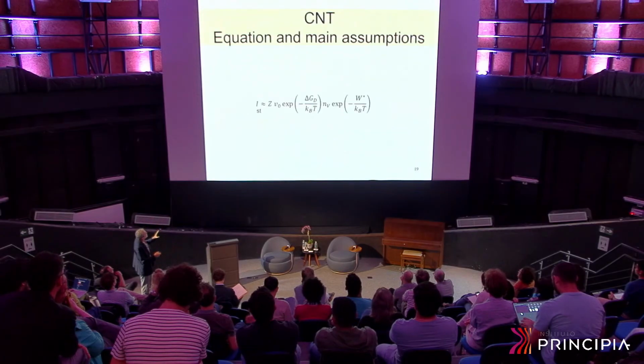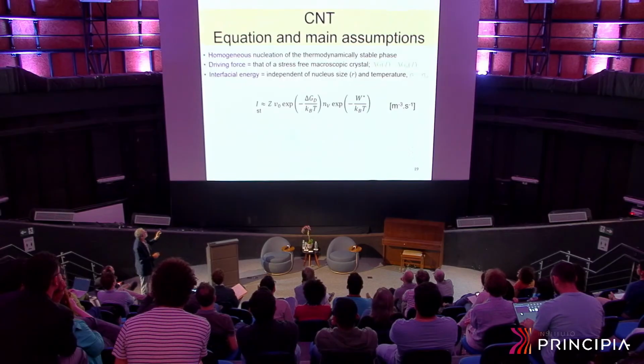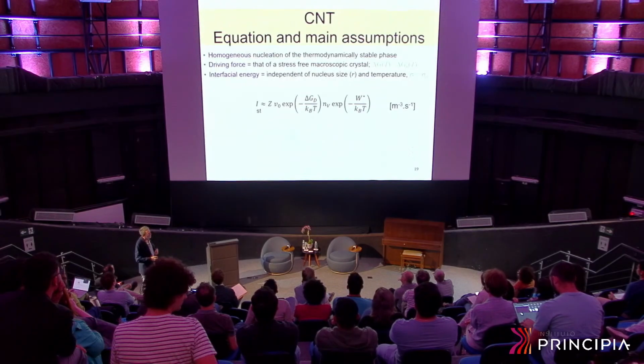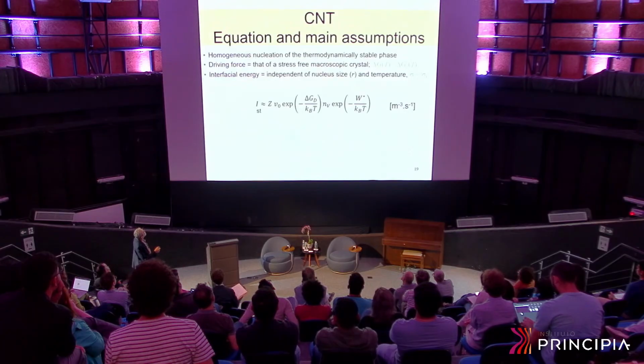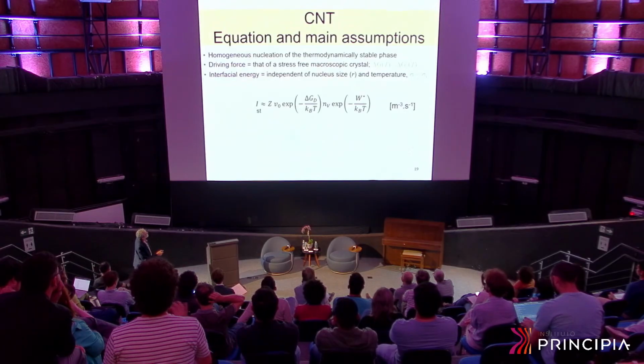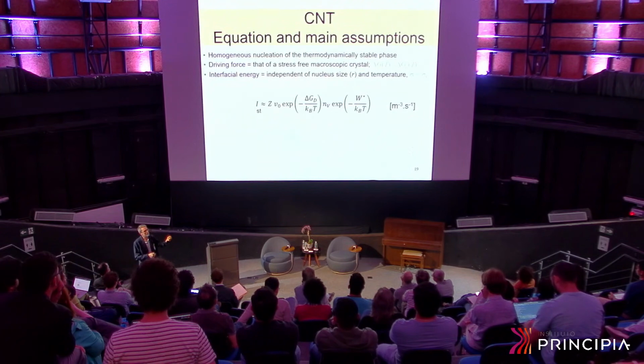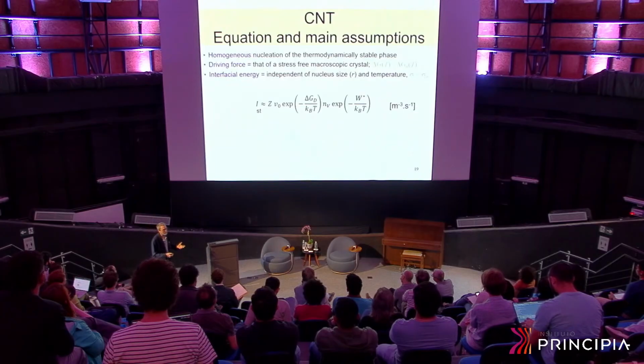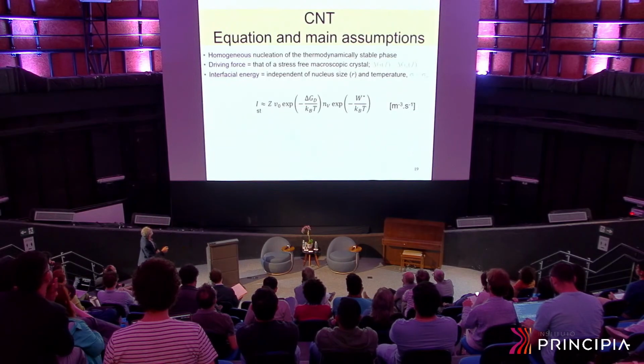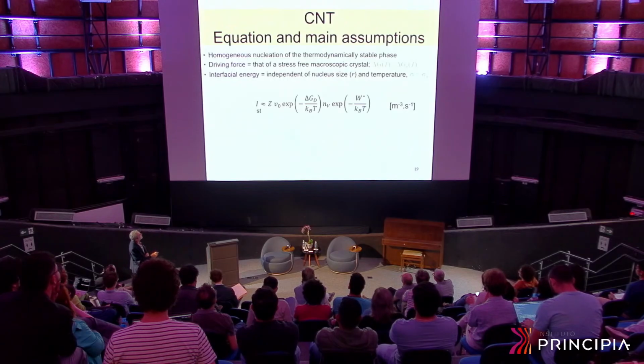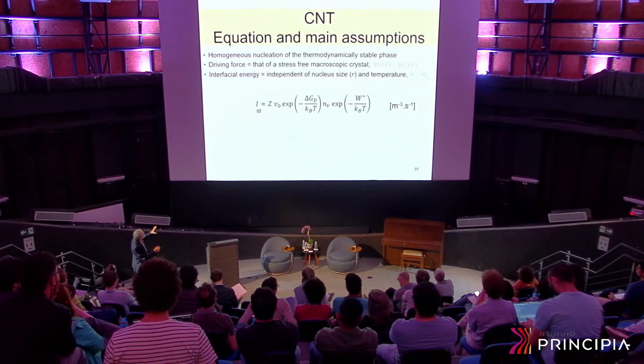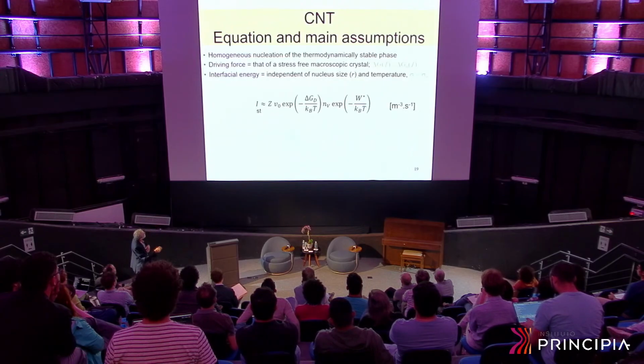So this is the expression, and then there are several assumptions. Of course, as most of these theoretical models, you have to assume that the driving force, the delta G, for a nano-sized crystal is the same as the driving force for a macroscopic crystal that we measure in the lab, that the interfacial energy is independent of temperature, etc. There are several assumptions, but with all these assumptions, this is the steady-state nucleation rate. This is the diffusion term. If you measure diffusivity somewhere, somehow, and then the W star, you can calculate